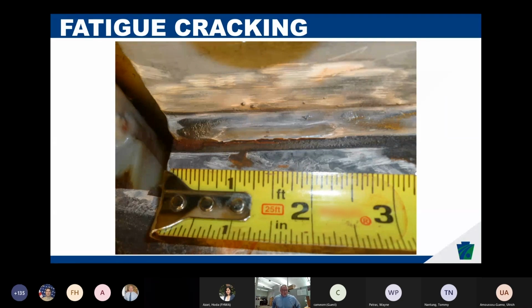Like I said, NDE for in-service infrastructure is really used as a supplement to aid in the visual inspection process. On some of the older structures where there's known fatigue issues, and there's something that hints to the inspector it needs a little bit more thorough investigation, we will apply some type of NDE measure to help them understand if there is some type of fatigue cracking going on there, which would not be apparent to just looking at it, right? In this case, I actually performed the NDE on this bridge, and you could not see the fatigue cracking without applying some type of NDE. NDE actually aided in the decision making for this particular structure to ultimately program, remove, and replace.